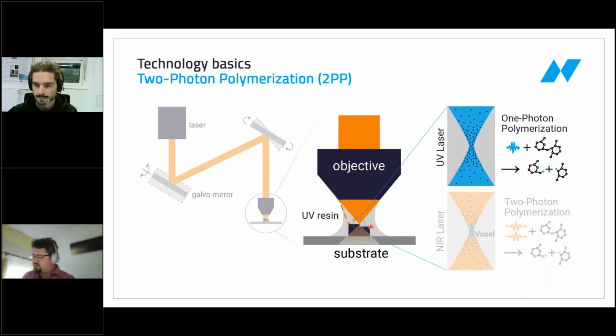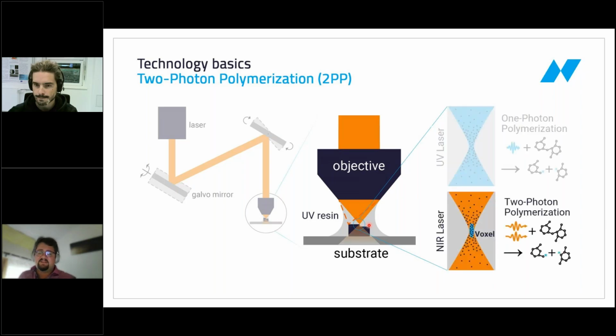And this is not a good way to do microprinting. So instead, we use a femtosecond near-infrared laser. Now the individual photons don't have nearly enough energy, so they just fly through the resin without any interaction, basically. But if you get close to the focal point, you can get to a regime where you have enough energy so that two photons can be absorbed at the same time, starting a cross-linking reaction here, but not elsewhere. And this is why it's called two-photon polymerization, and it gives us a very high degree of confinement.